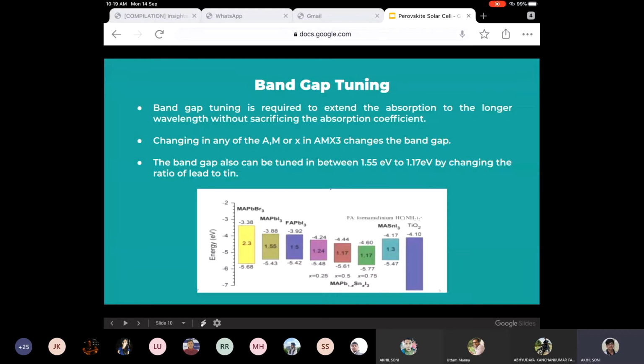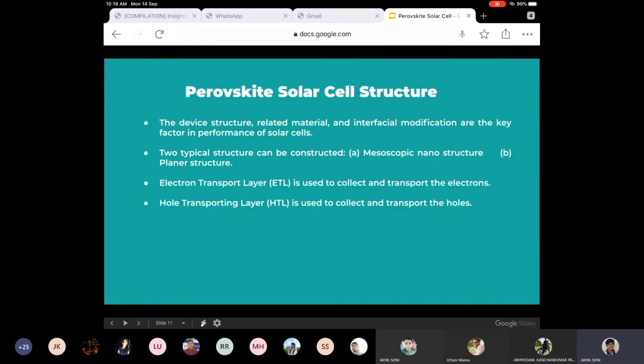Like we can see in the photo, MAPb1-xSnxI3. As we change the x, meaning the Pb to Sn ratio, the energy difference, that is the band gap energy, changes. Like for x equals 0.25, the band gap energy is 1.24 electron volt, and 1.17 electron volt for x equals 0.5. So there are different ways to change the band gap. Now I will discuss the perovskite solar cell structure. The device